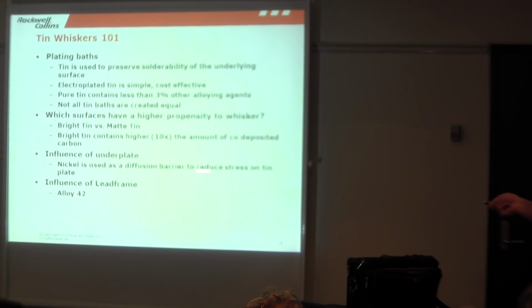If you put a nickel barrier over, typically you have a copper lead, you're gonna put a nickel barrier down there. Nickel, and how you control the intermetallic between the tin plating and whatever metallurgy is below it, helps a lot. And tin and nickel form a very laminar, very smooth intermetallic, and I'll talk more to that, but being able to look at the influence of what having a barrier layer does will help you out in some cases. The lead frame, alloy 42.